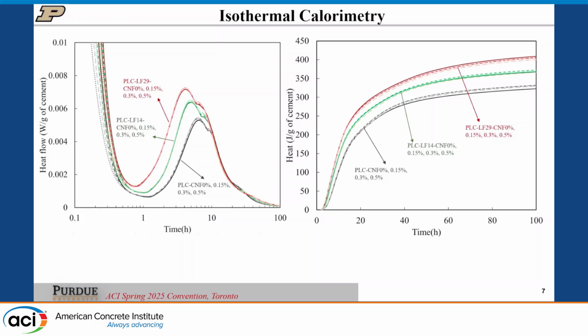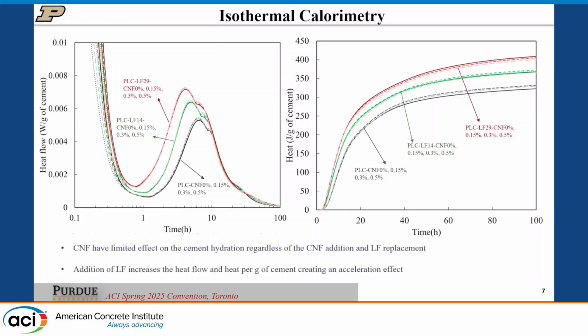For the black line, you see some dotted lines around each of these lines. The dotted lines are the mixes with CNF content, and when the color changes from black to green to red, this is changing the content of limestone filler. What we really found is that CNF is not significantly changing hydration, at least not at the quantities we're looking at. But with the addition of the limestone filler, we're seeing somewhat of an acceleration effect - the curves jump to the left, and we see an increase in heat of hydration. This is not because the limestone filler is hydrating, but because it's giving us a lot of particle packing density that's helping with our system.